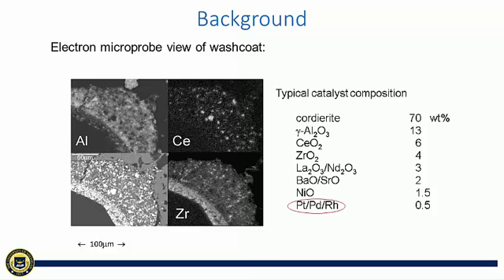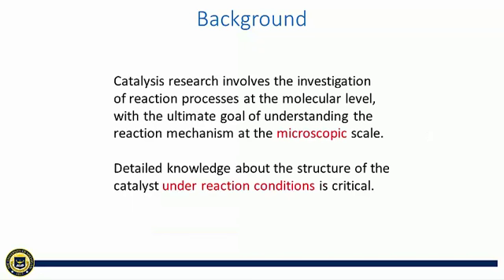The most important component, however, is the precious metal, usually a mixture of platinum, palladium, and rhodium. These metals, in the form of highly dispersed nanoparticles, provide the active surface sites where the chemical reactions actually occur through a sequence of elementary steps, including adsorption of molecules, breaking and reforming of intramolecular chemical bonds, and desorption back into the gas phase.